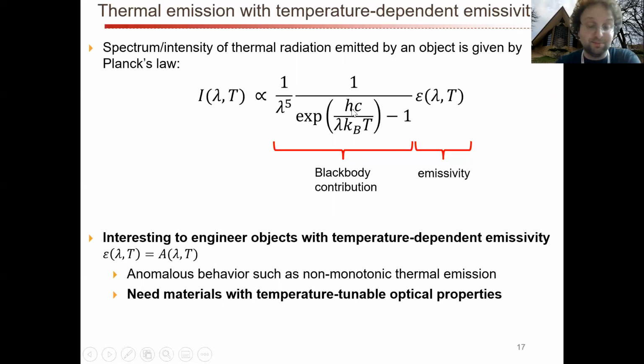You can imagine some really strange behavior, such as you're increasing the temperature and your emissivity goes down so much that the overall thermal emission goes down. That's a very strange situation. And so if you want to play these kind of games, if you want temperature as an engineering knob in your toolbox of engineering thermal emission, you need materials with temperature tunable optical properties, and this temperature tunability needs to be very, very large, right? Because this blackbody contribution changes quite rapidly as a function of temperature, and therefore this emissivity also has to change quite rapidly. Otherwise, you can essentially neglect that temperature dependence.